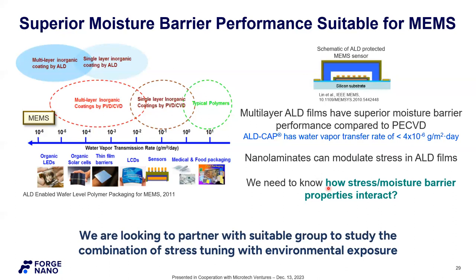One of the aspects here that is very little talked about is how stress, which I just talked about, and moisture barrier performance interact. It's well known that as a film absorbs water, the stress can change, not just ALD films, but pretty much every thin film. So how the stress and moisture barrier properties interact is not something that is well understood. And it's another topic that we're looking to collaborate on